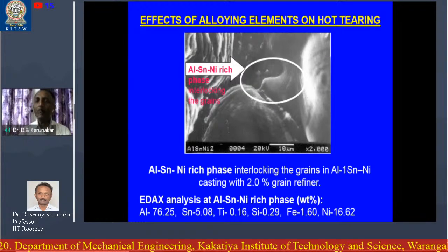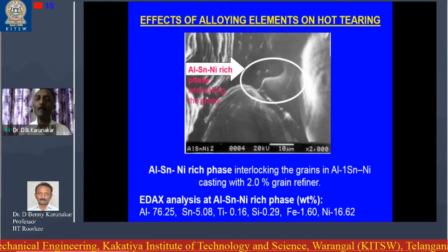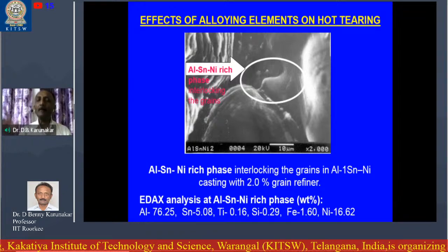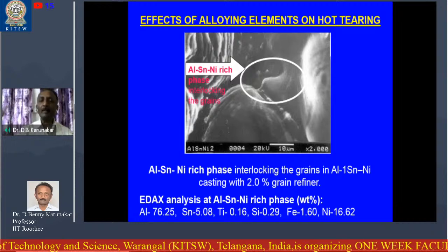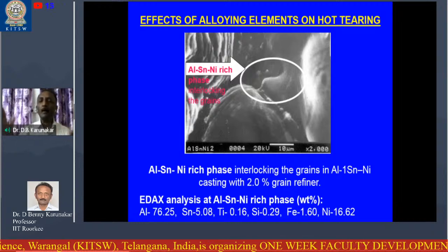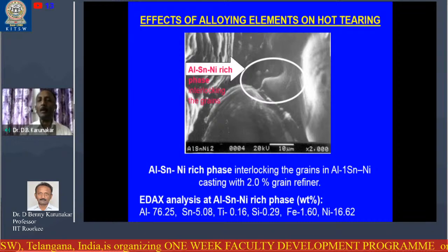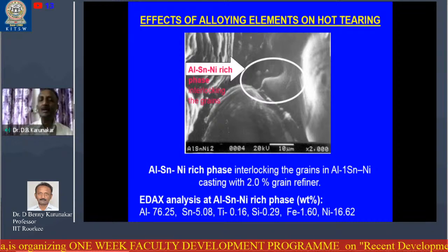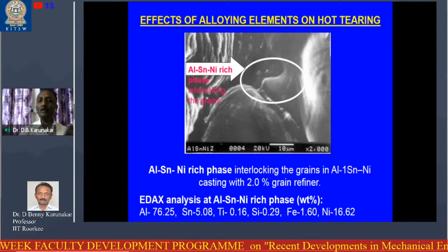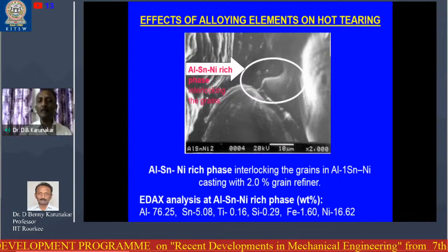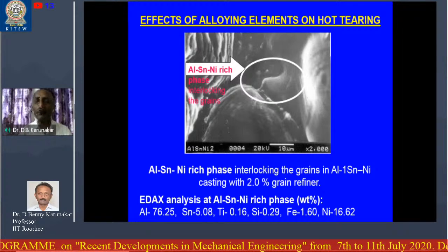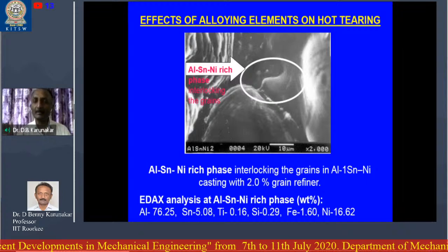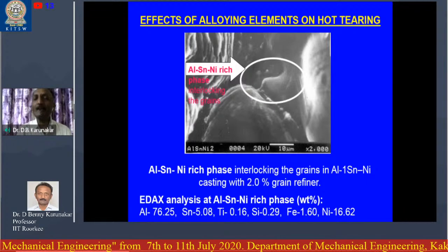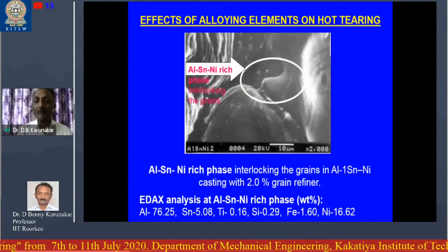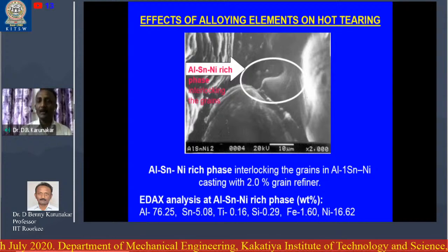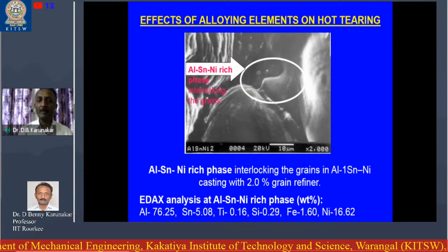When the aluminum grains started undergoing solidification, and after solidification was over, when they were about to become smaller or undergo contraction, this nickel-rich phase was holding them together and prevented further movement. That is how hot tearing was prevented. Nickel is a common alloying element, so fortunately it helps us prevent hot tearing in aluminum castings.